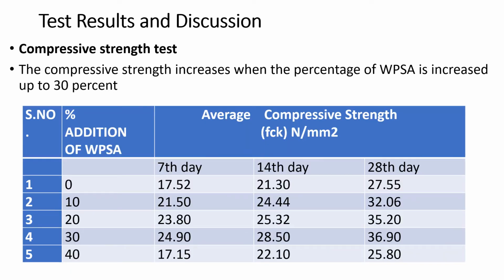So let's look at the test results, and the first one is the compressive strength. As you can see in the table, the compressive strength basically increases when the percentage of the waste paper ash increases, but this increase is only up to 30%. If you increase the percentage of the ash more than 30%, then the compressive strength basically reduces. This is applicable on the strength at 7 days, 14 days, and also at 28 days.